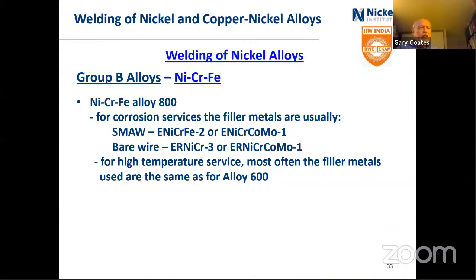So moving on, or getting back to the nickel alloys and the group B ones, the nickel chrome iron 800 is a common alloy. Now it is used both for corrosion resistant services and high temperature. So when it's corrosion resistant, you typically use a nickel chrome iron 2 or nickel chrome 3 filler metal there. If you want a little bit higher strength, you can use one that contains some cobalt and molybdenum.